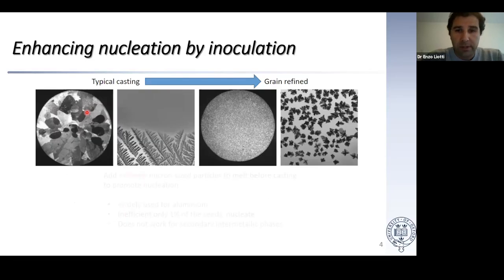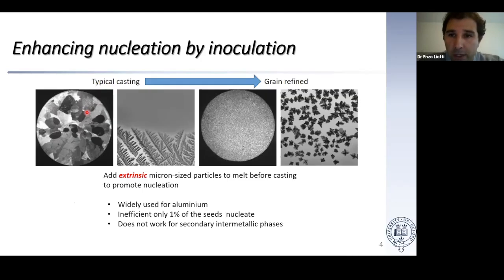For aluminium, the most used method to obtain an equiaxed microstructure is to inoculate. Inoculating means that you add micron-sized extrinsic particles, so they don't dissolve in the liquid metal, that act as nuclei and basically enhance heterogeneous nucleation. This technique is widely used in the aluminum industry, and there is one particular particle, called titanium diboride, which is ubiquitously used for aluminum. However, the process is very inefficient. Only 1% of the seeds added nucleate, and this has actually already been optimized over decades.